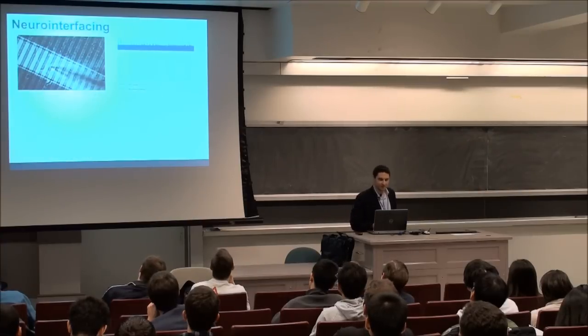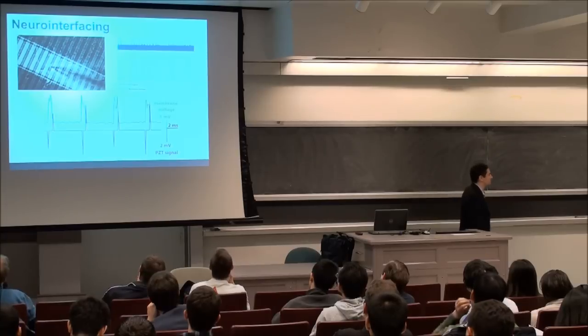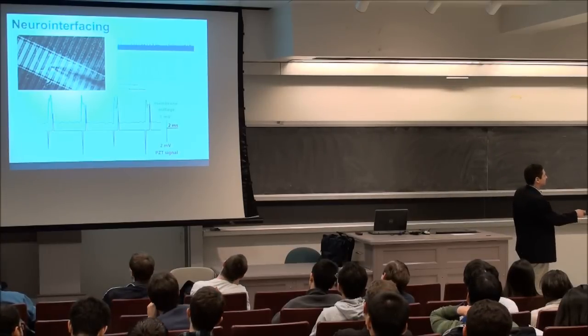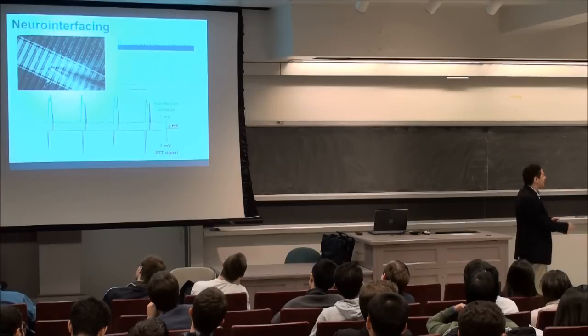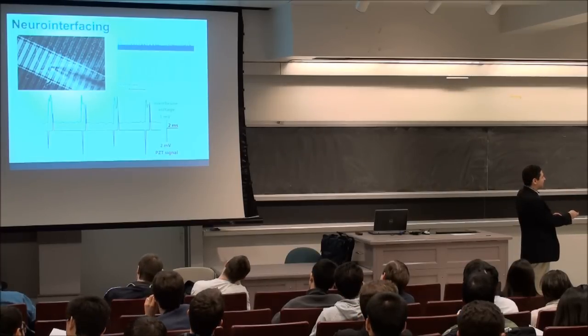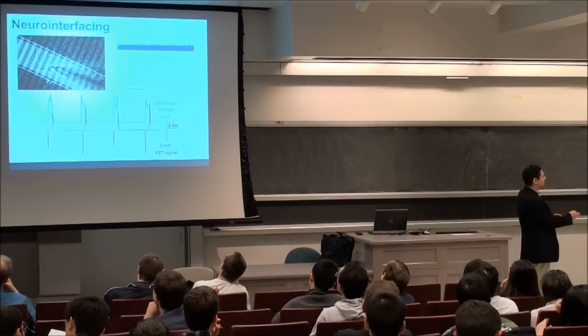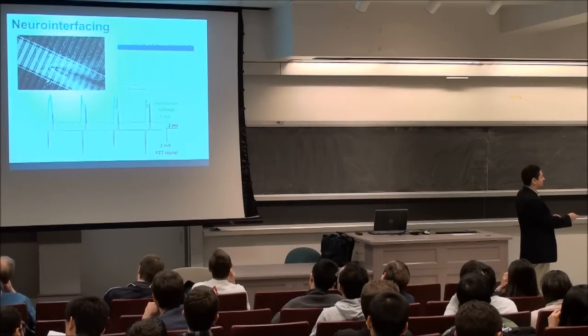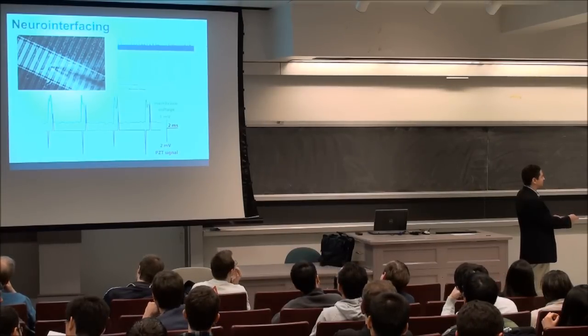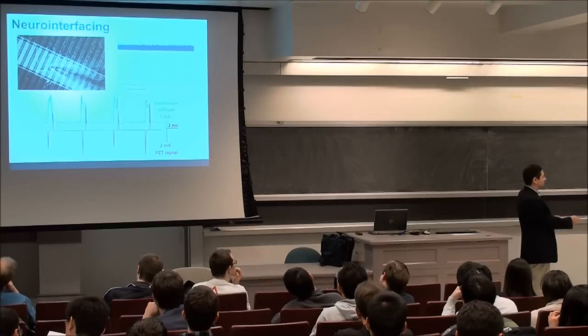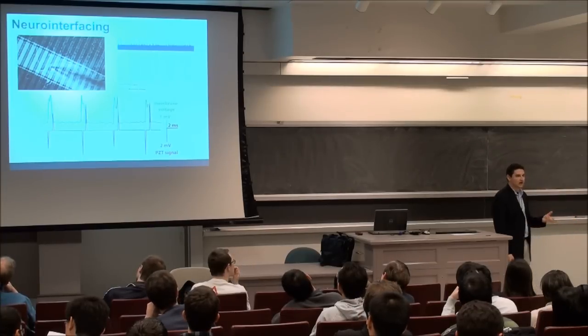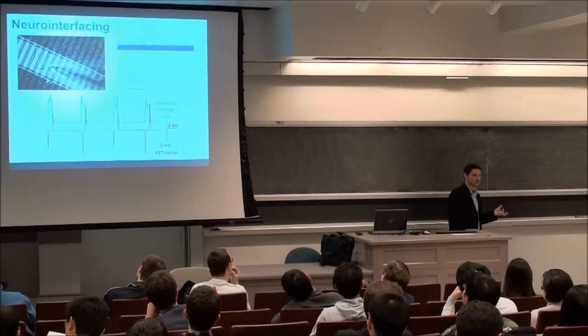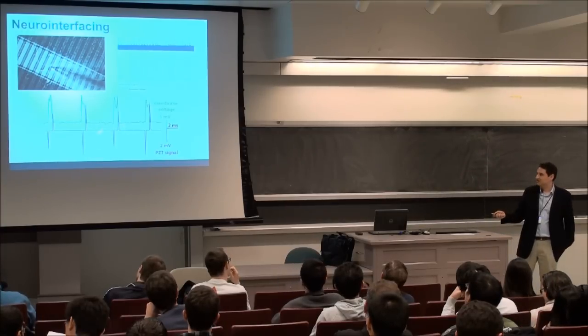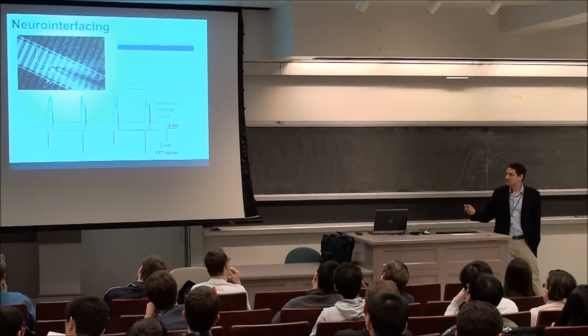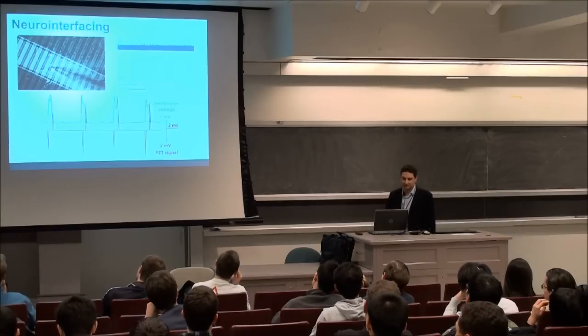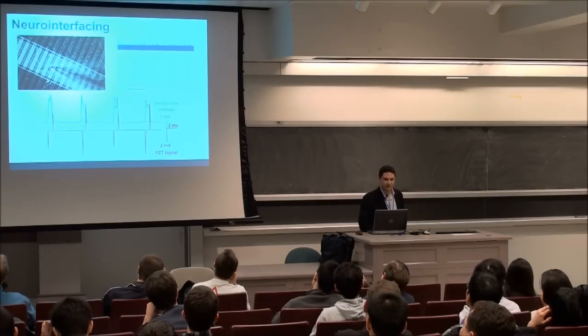So then we measured it here. You can see this amazing result that we got where we put down this patch clamp probe on the ribbon. We depolarized the cells, and you can see every time we depolarize the cells here, we got this spike in the PZT response. So here it's blown up. We get this perfect AC spike in our piezo response every time we spike those neurons. Okay, so we are actually able to measure with this sensitive cantilever system. This paper is under review right now in Nature Nano. We're able to measure this flexoelectric response in the cell using this piezo system.